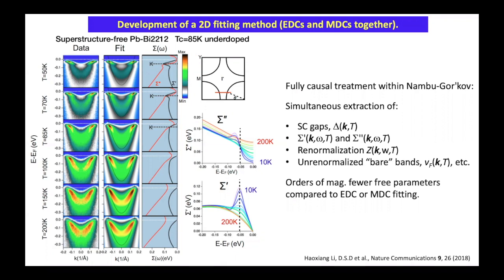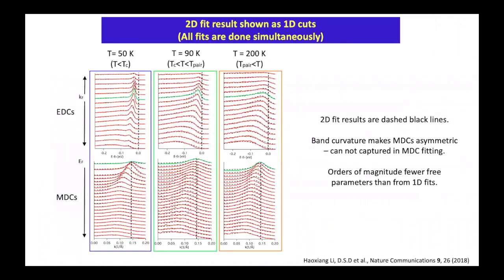As I go through Tc, I have a huge drop in sigma double prime. Of course, there's a gapping of the spectral weight as well. These are the sigma prime and sigma double prime as a function of temperature and frequency that make each of these fits that are all working extremely well. Well, those are 2D fits. If I look at 1D lines of EDCs or MDCs, the red is the experimental data, the black are fits. They're not perfect, but they're actually really good. They're better than I could do from a single EDC or MDC because of the asymmetry.